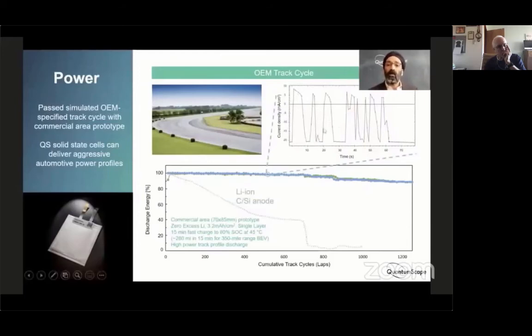And then in between those discharges, we recharge this battery in 15 minutes. So a really fast recharge. So the way this test works is you drive around the track 9 times, and then you recharge it in 15 minutes. Just to be clear, this test was run on our single layer pouch cells, so we didn't actually put these cells into real cars. Well, we don't have production cells yet, but we are able in this single layer pouch cell to stress it using the same current densities that the cell would experience in a vehicle driving around the track.